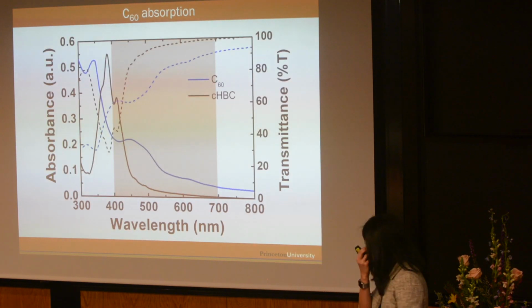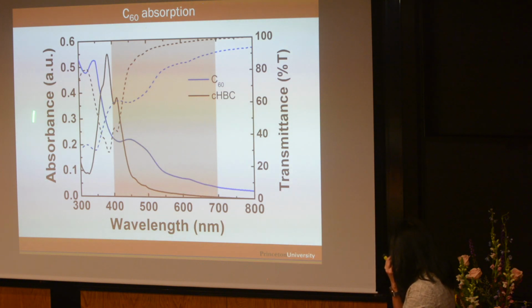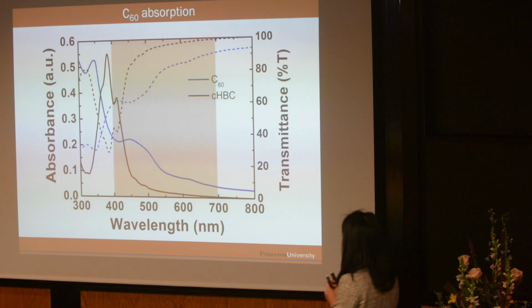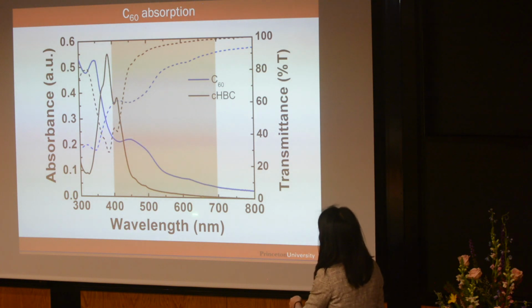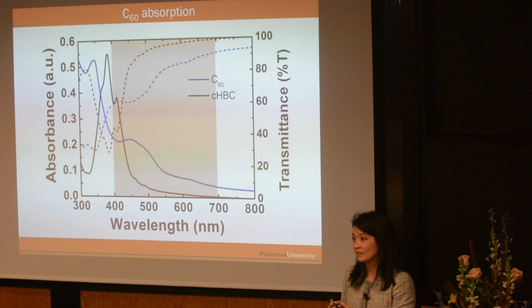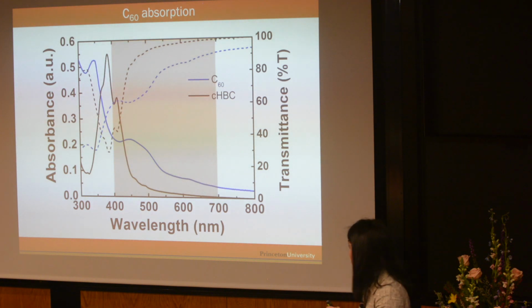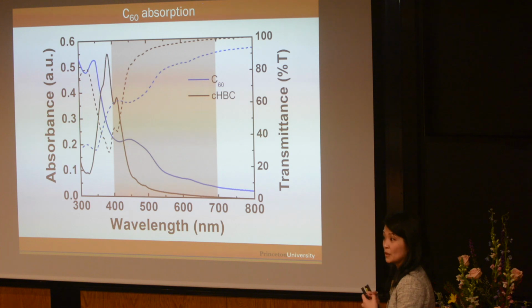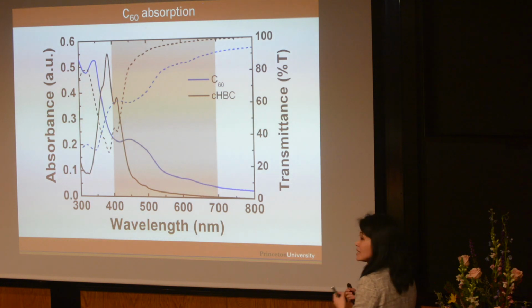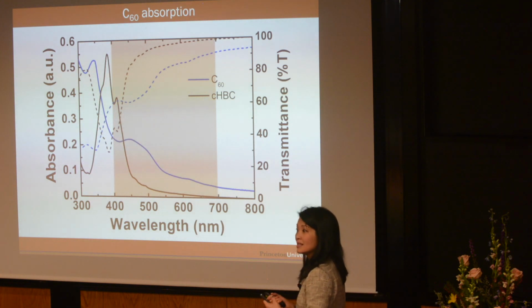Now, if you look at the absorption, that's plotted in solid lines, or you can look at the transmittance, that's plotted in dashed lines. What you'll notice, again, this is the visible range, is that we have significant absorption by C60. Okay, so this is not a transparent cell. This is not sufficiently transparent for our application. So this told us that we needed to replace C60 with something else.